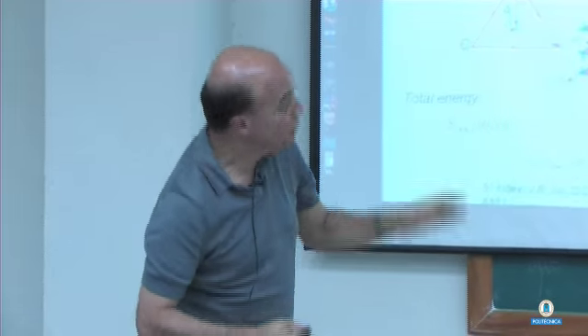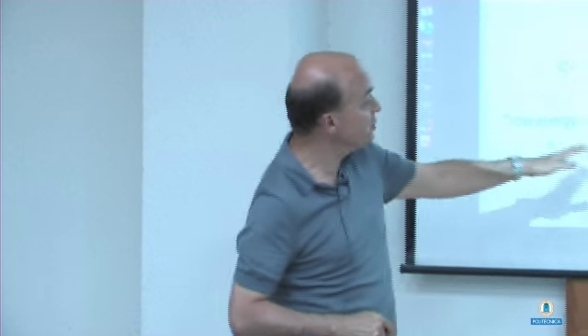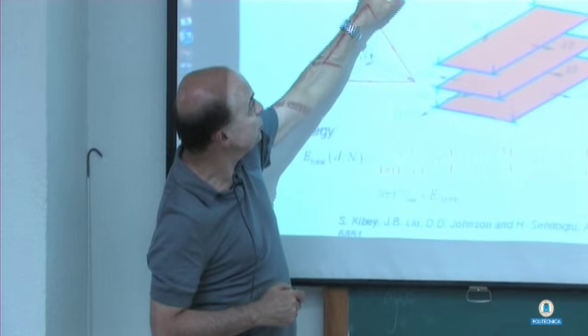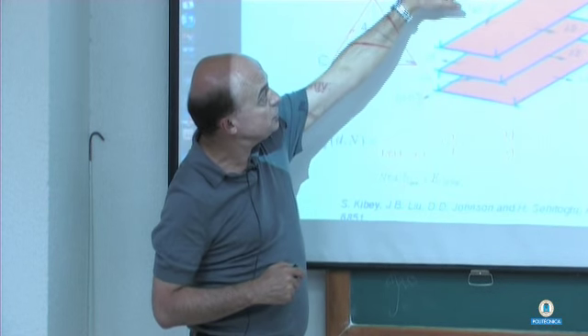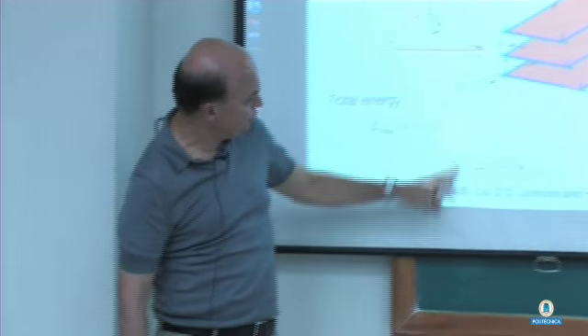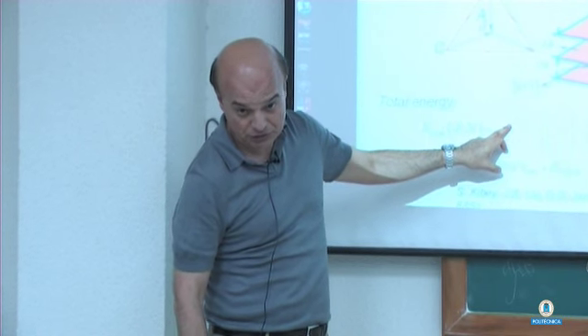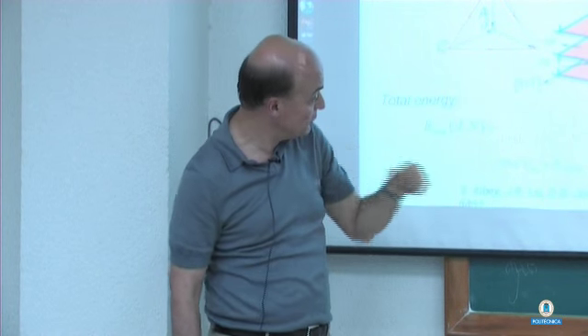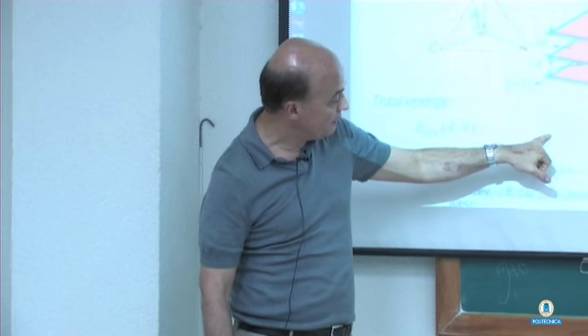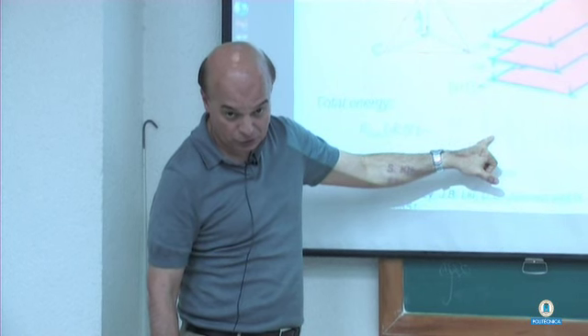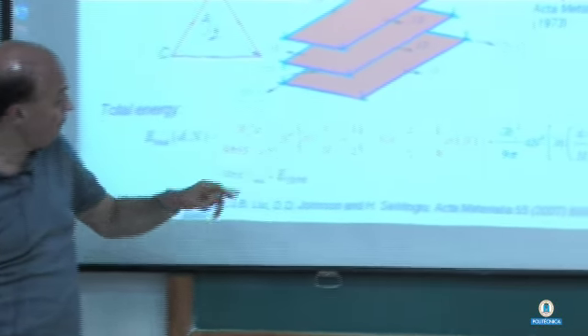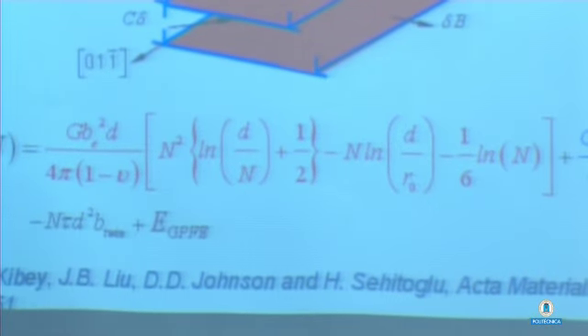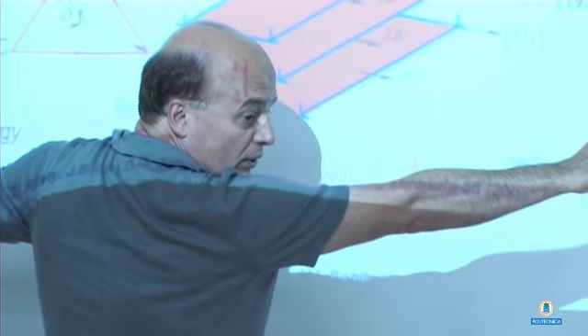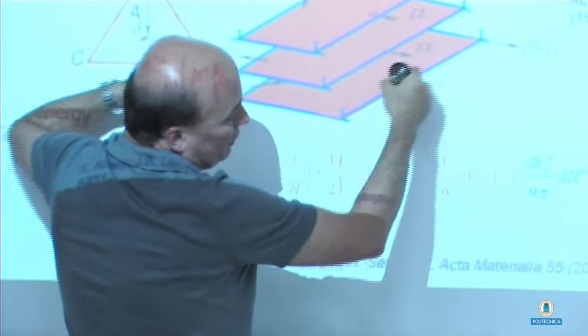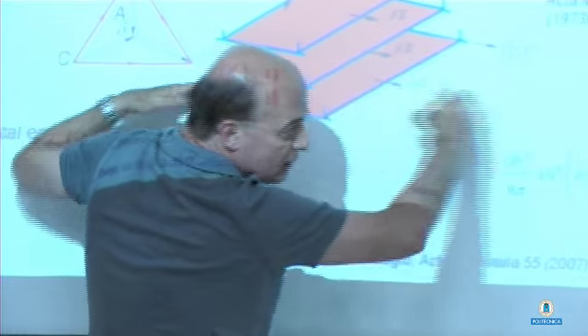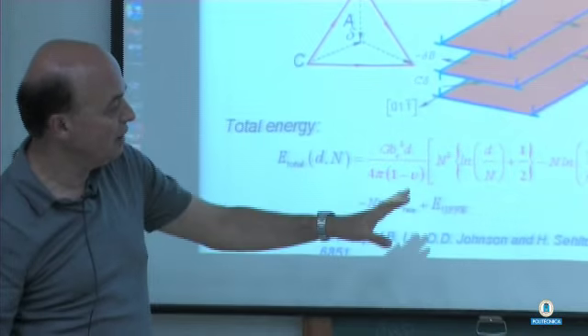So if we have this entire energy expression, we have a total energy expression. The red is the energy contribution of edge components, blue is the energy contribution from screw components, and if you look at the terms here, there is a shear modulus, but we determine that from our calculations. Burgers vectors, they're known. This is the number of layers in the twin nucleus, which will be 3 in our model, and D is unknown. That's the twin length, if you like. This is the twin width or length of the twin. That's D. So that's an unknown parameter.